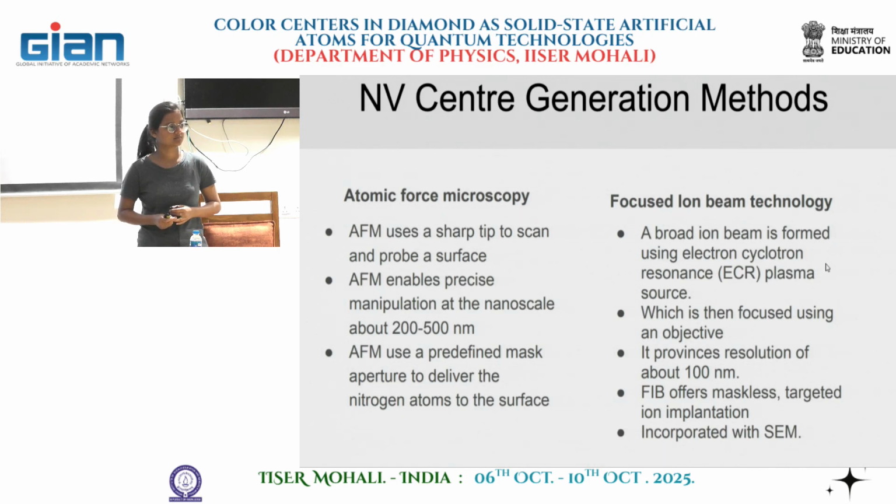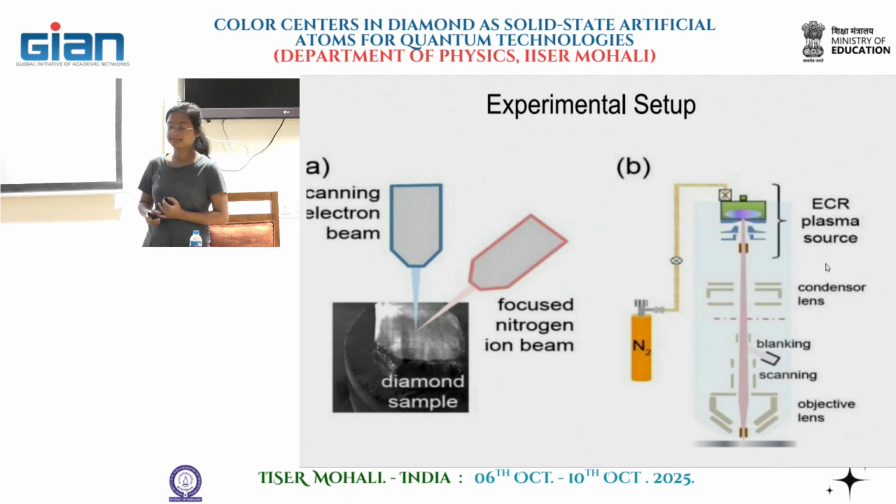And we actually tried after that to see whether or not we could have higher resolution, and this is a little bit difficult. It's not so easy to have higher resolution, due to the fact that if you come back to the column of the machine, where there is the plasma source, you have a hole, and it's basically that hole that sets the resolution of the whole column.